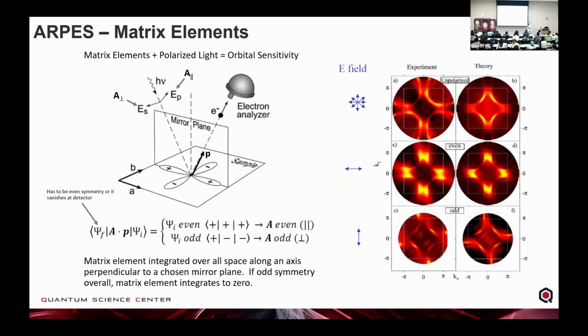Matrix elements. Another unique thing about this is we can actually have orbital sensitivity to our electronic structure. If we have, right here, this sort of d-wave orbital, then at the detector the wave function has to be even or we won't see any intensity at the detector. Now we have a mirror plane, and there are selection rules based on the vector potential of the light hitting the sample and the momentum of the electron propagating away from the surface. By looking at this mirror plane, and whether it's even or odd symmetry based on this scattering plane, we can set up selection rules that either enhance or suppress the intensity based on the symmetry of the orbital. Here you can see that this has even symmetry.